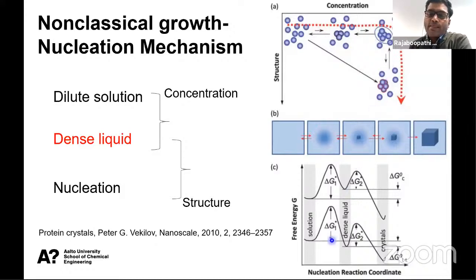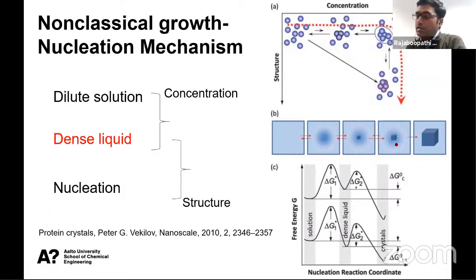This is non-classical growth, and this is the Gibbs free energy change in the non-classical system. So sometimes in the non-classical growth, after forming the nucleation cluster or the nucleus, they will attach together like this. The attachment is not random, it has some orientation. So we call it mesocrystals. Mesocrystals are crystallographically oriented nanoparticles. You can see further what mesocrystals are.